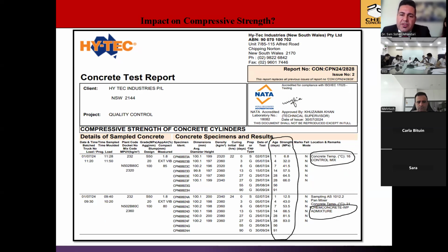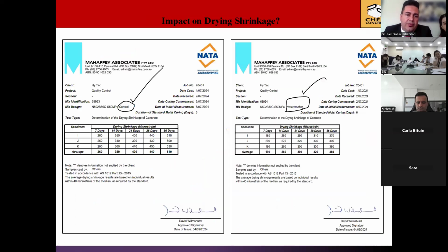You can see another mix design. The 1 day compressive strength was 6.8 for control, 12.5 for concrete containing our admixture. You can see a somewhat similar increasing trend was observed in other curing days. And this is particularly good, as it allows construction companies, especially precast concrete manufacturers, to remove formwork at a much shorter time compared to normal. So it saves time and money.